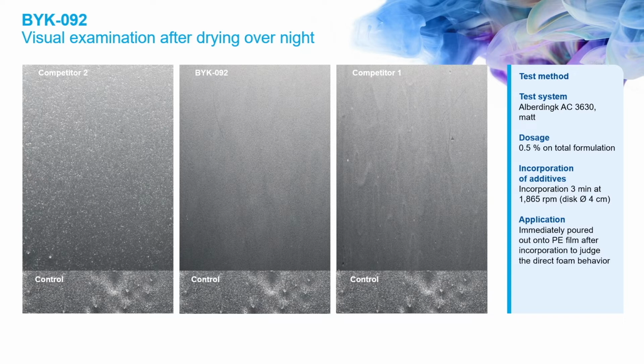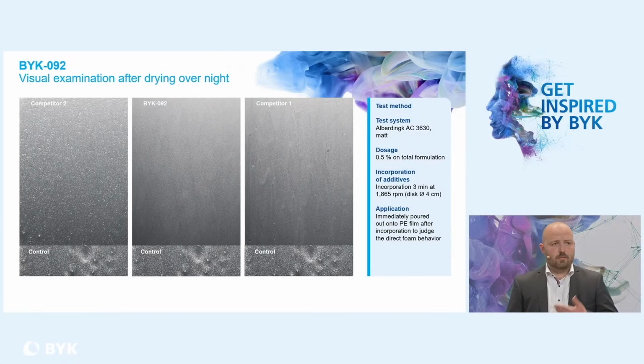In the middle, the BYK 092 has a really nice surface, a very good result, while on the right-hand side you can see that the surface defects that you've already seen in the wet film still remain in the dried film, so also not an ideal solution, while BYK 092 is really giving you very good properties.